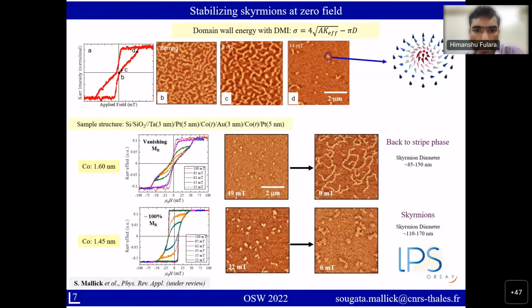Okay, this is a nice question. There are some ways to distinguish magnetic bubbles and skyrmions. The best way to distinguish between them is to apply some current pulses and to check if they are moving with the current pulses or not. This is the best way. If they are magnetic skyrmions, they will move. If they are bubble domains, they will not move.